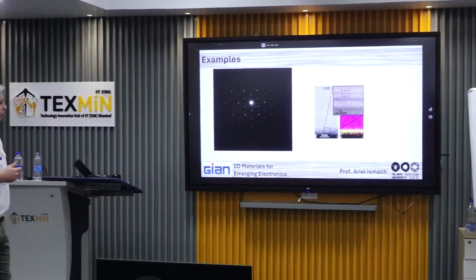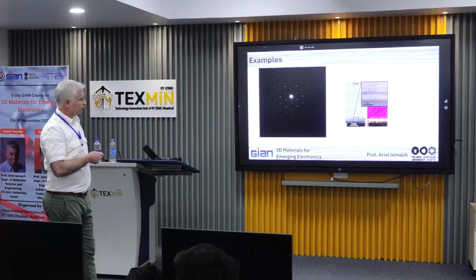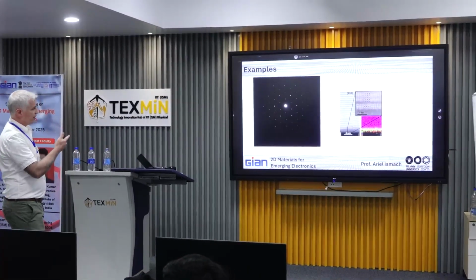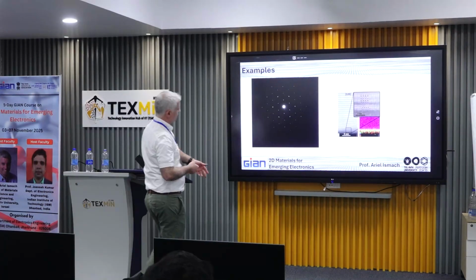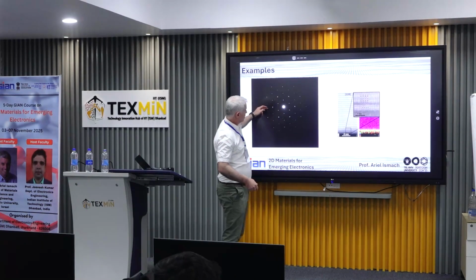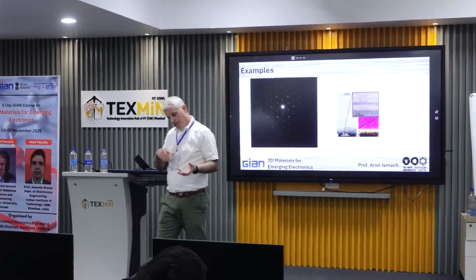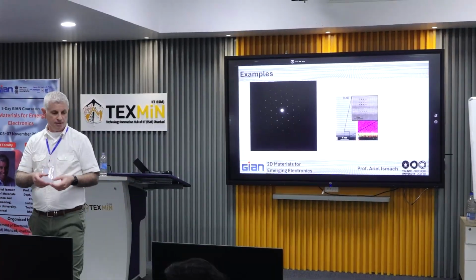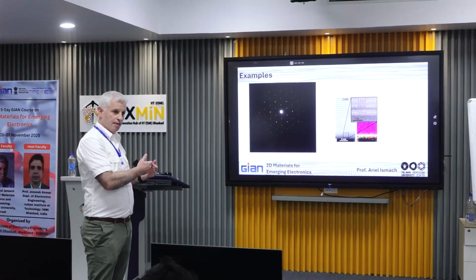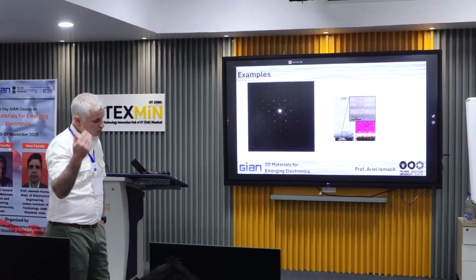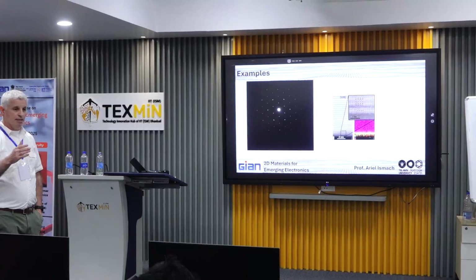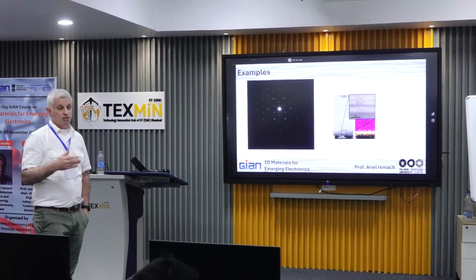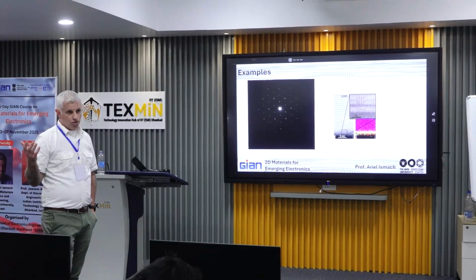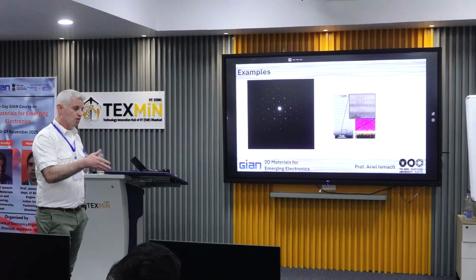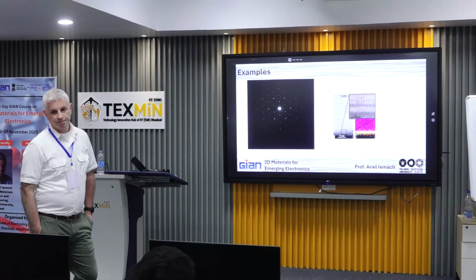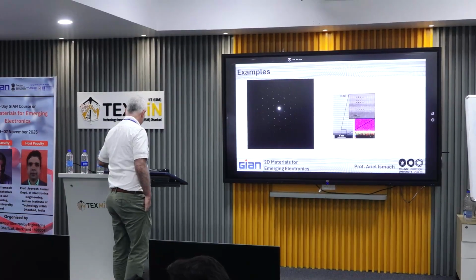And also, in order to be sure that the phase or structure that you're measuring fits the pattern, what you need to do is measure the spacing between the peaks, and then there are ways to calculate from that the plane that is giving this diffraction. You compare that with databases, and you know what materials you have in your sample. It's much harder to identify a material when you don't know if it's in your sample or not. But if you know what material you're looking for, it's fairly easy. Okay, questions?